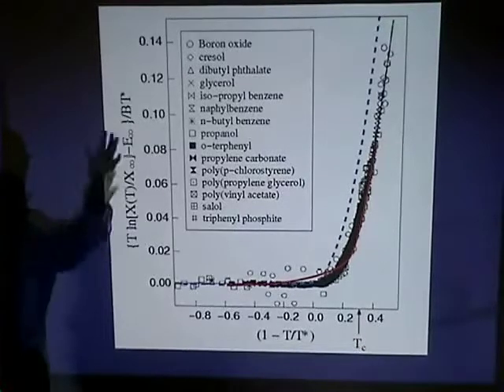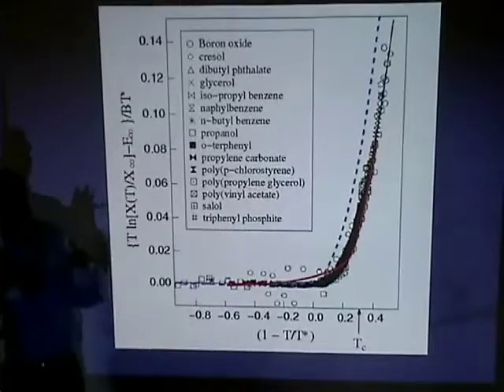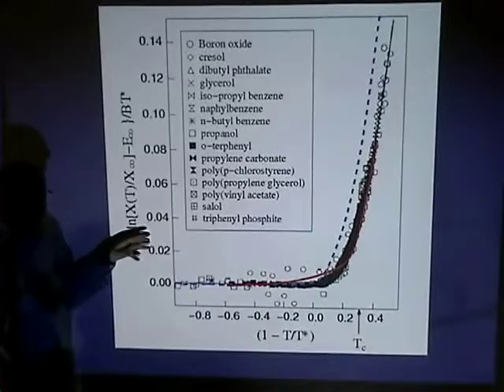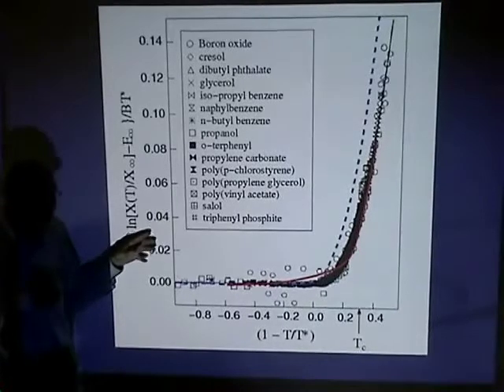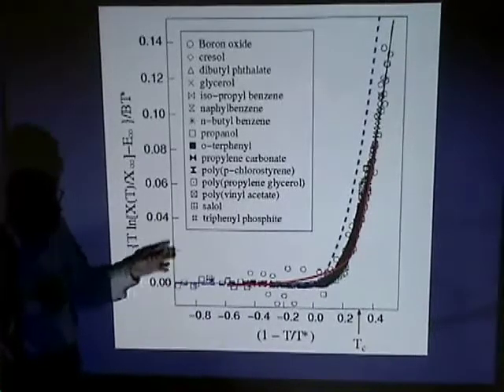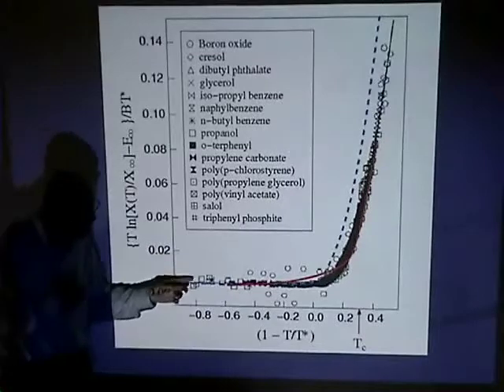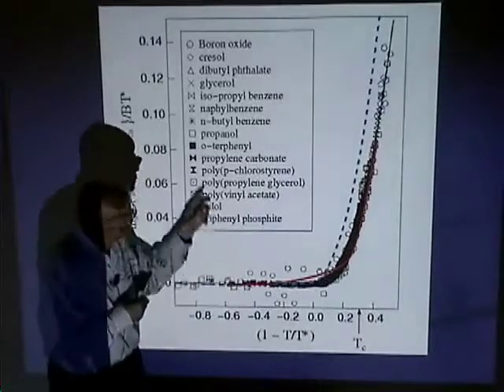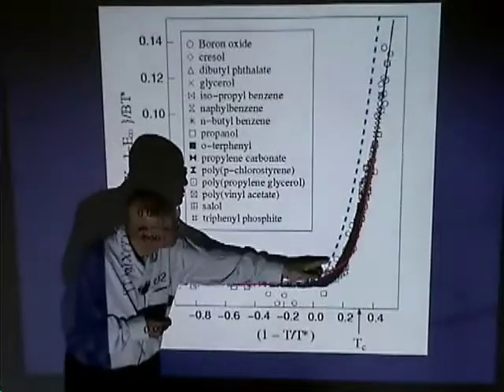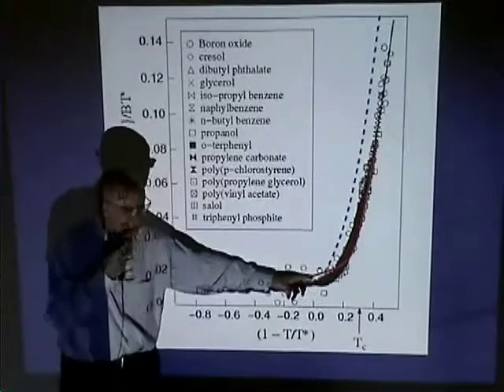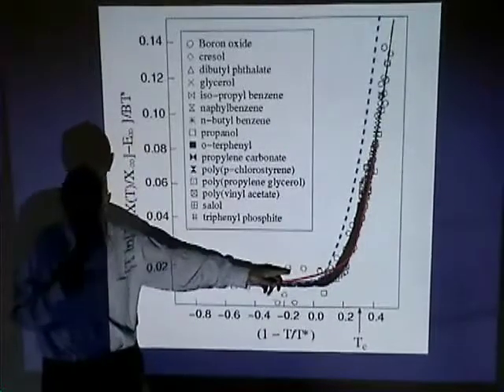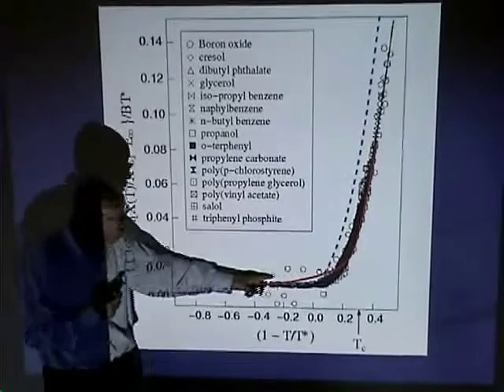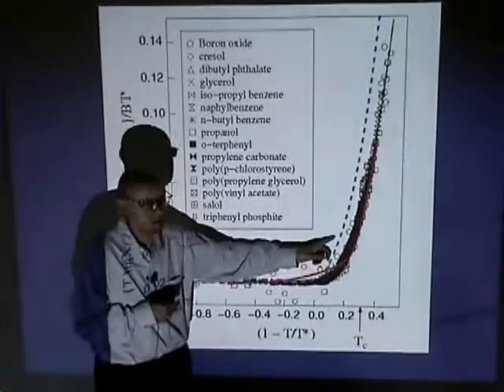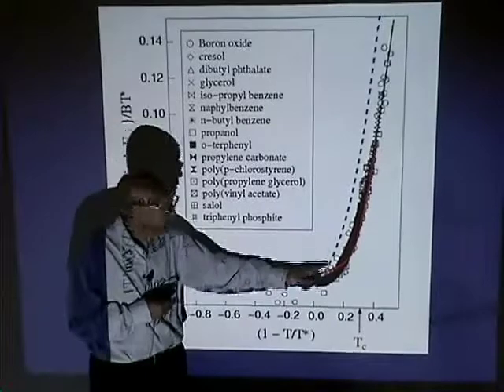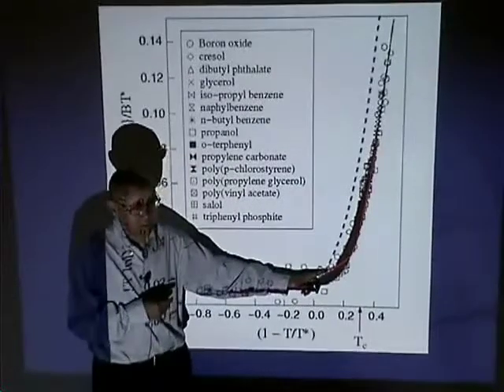They took all these liquids, massaged it a little, and fitted it to an activation barrier as a function of temperature. So this is their way of plotting it. We simply took their data. All these symbols are data, except the two curves of interest to us: the heuristic model is the dashed curve, and the Green-Kubo model is the red one.